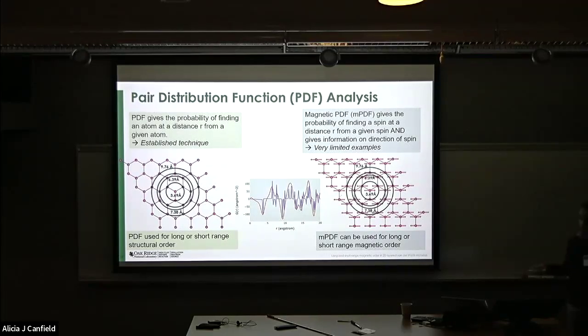It's used a lot to look at long range order, short range order, distortions, glasses, very large unit cells, and so forth. So more recently, people have started looking to see if they can do magnetic PDFs, instead of looking at the atom-to-atom distances, whether they can look at the spin distances. Okay, so magnetic PDF gives you the probability of finding a spin at a certain distance from another spin. Okay, so there's very limited examples, really just a handful, probably half a dozen or less that have been reported. But if you can start to use it, then you can start to analyze long and short range order in a single technique.